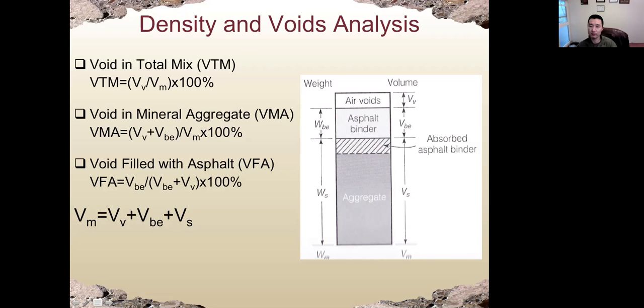We also have asphalt binder, which is VBE, where E is for effective. So that's the asphalt binder which is not absorbed on the surface of aggregate. We also have a small percentage of air voids in the system. The percentage of air voids is very important for asphalt concrete because the more air voids, the faster the aging process, because in the air we have oxygen, and oxygen will accelerate the aging process for asphalt concrete. Because of that, we have many different types of voids.